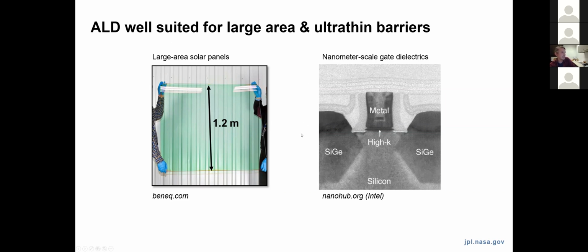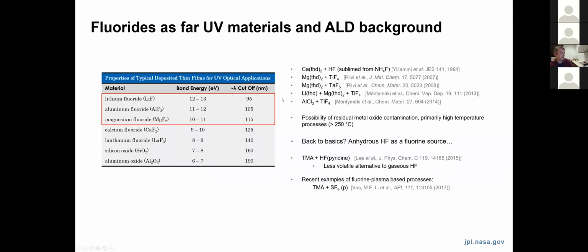It's already widely used in the display and large area solar panel industries. And as I mentioned, it's also widely used for semiconductor applications for these nanometer scale coatings. So we want to utilize these very thin coatings over very large areas, as I'll describe for this particular application. Since we're mostly interested in extending the short wavelength performance of these optical systems, we're again stuck with considering protective coatings that can maintain transparency to as short a wavelength as possible. And so again, we're limited to this handful of metal fluoride materials that we could potentially use as a protective coating on aluminum. So in order to use those materials with ALD, we needed an ALD process and the appropriate reaction chemistry that can produce them.